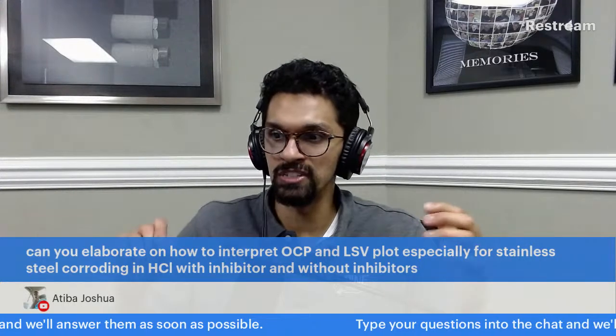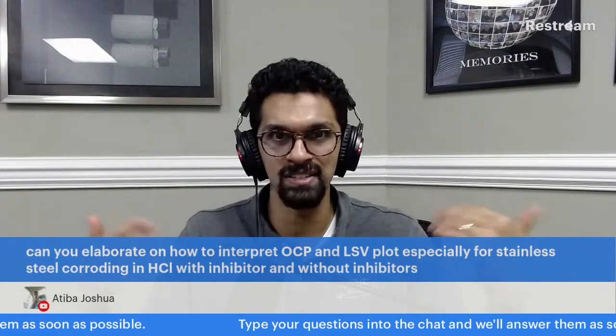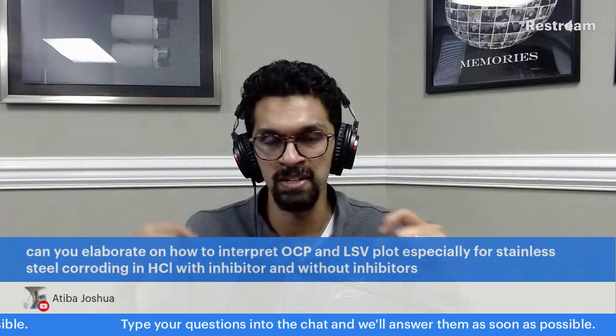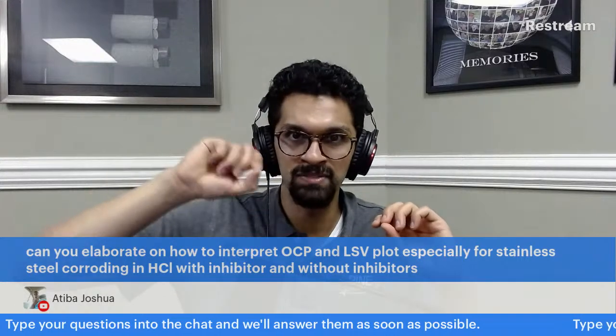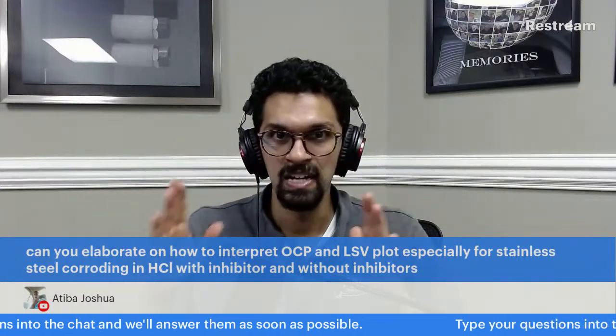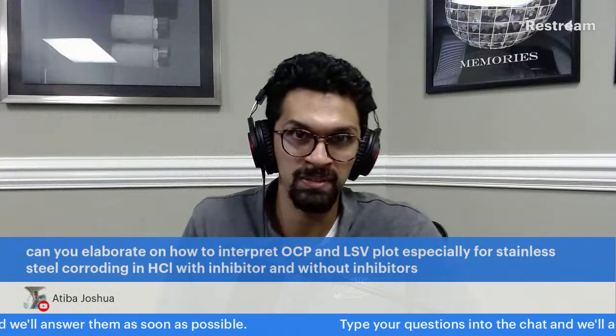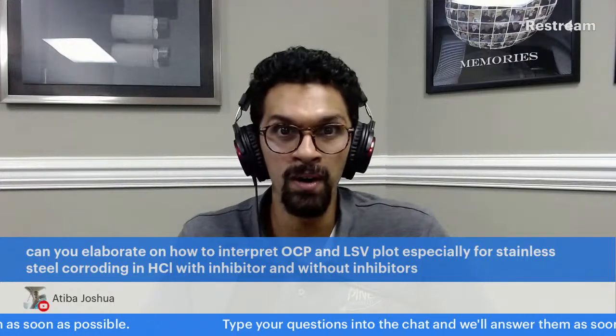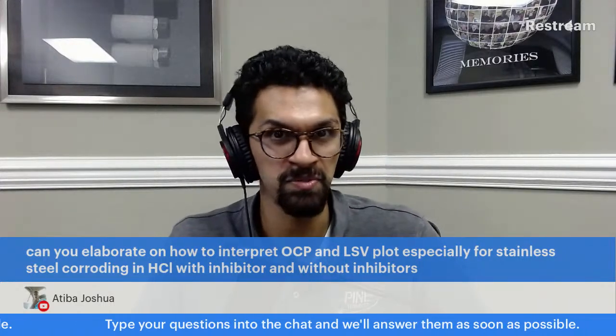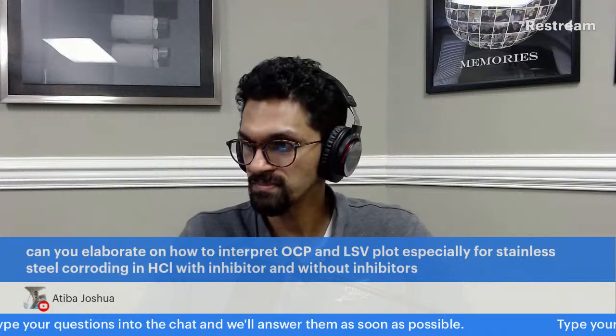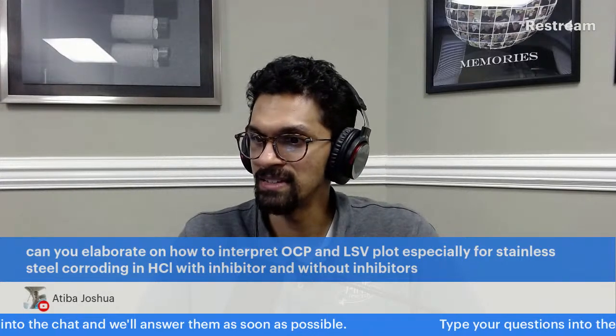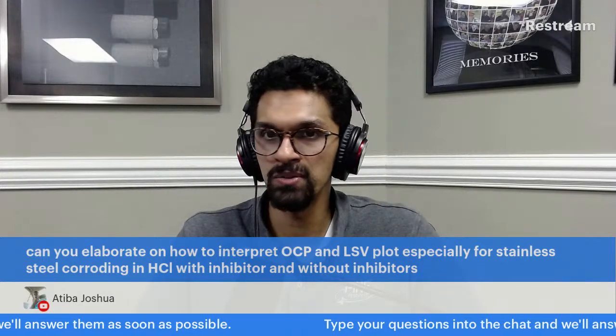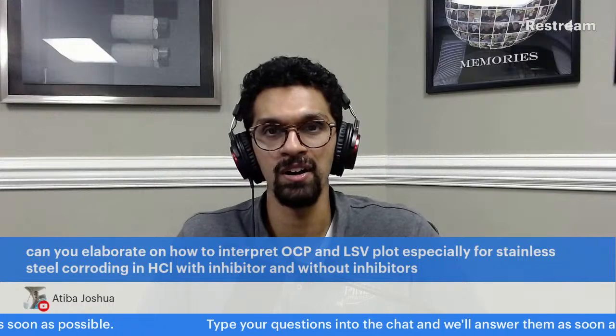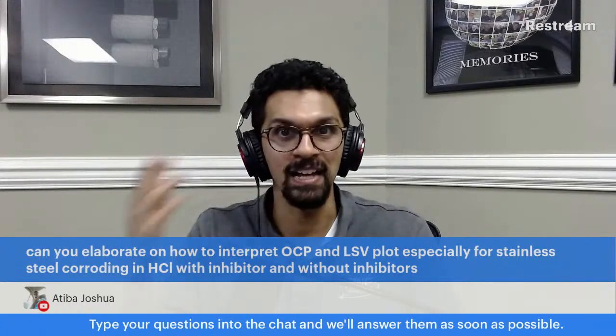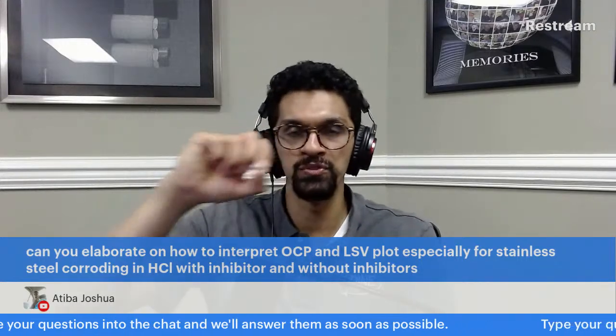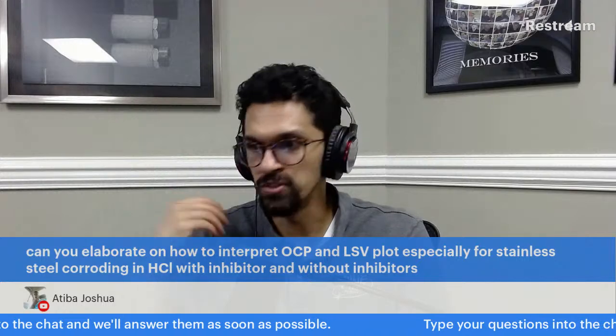And usually you do multiple cycles of this, like, you look at the OCP, do a little bit of this very small CV. It's like plus minus 10 millivolts at maybe 0.1 millivolt per second. So it's a very slow scan. And then that's like one LPR cycle or iteration. And you just do a few of these with no inhibitor.